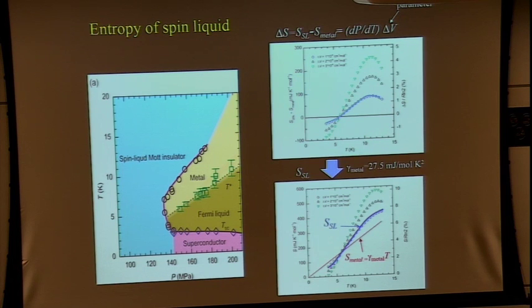Okay, so this is an entropy difference, and assuming the entropy in the metallic state is like this, gamma T, the gamma is inferred from the spin susceptibilities under pressures by using the Wilson ratio of 1. In the metallic state of this family of materials, many materials show the Wilson ratio of 1. So the gamma is guessed to be 27 or 28 millijoule in this material. So this is the inferred spin entropy of the spin liquid. Okay, this is around 5 or 6 kelvins.